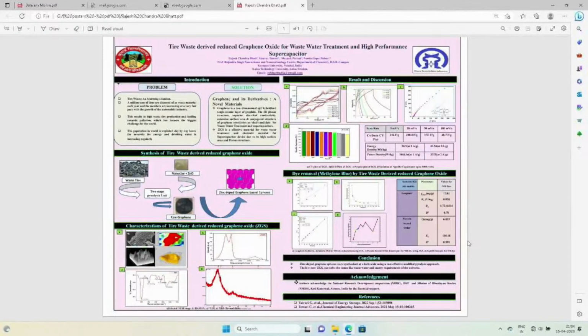Further, we used this material for wastewater treatment. This is the Langmuir plot and kinetic plot, and these are the parameters of these plots, and the RL value in the Langmuir plot shows the adsorption is favorable. So the conclusion is we have successfully synthesized reduced graphene oxide from waste tire, and we successfully showed the application of this material in wastewater treatment and the energy crisis.